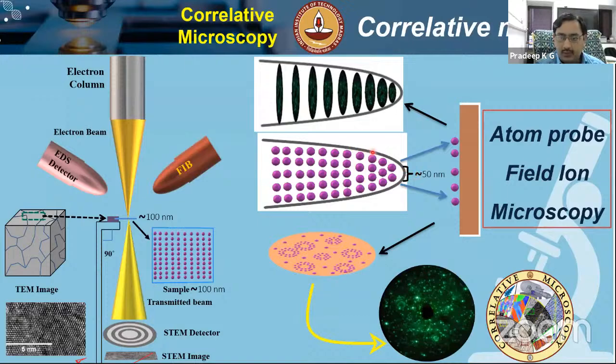But significant modeling is required over ranges of these kinds of surfaces to see what potential exists at the surface at what distance. This will enable us to go back and verify whether there is any distortion associated with this evaporation. So both these issues, distortion in the atomic positions with respect to the applied field and missing atoms because of detection deficiency, can to a large extent be overcome with computational effort.